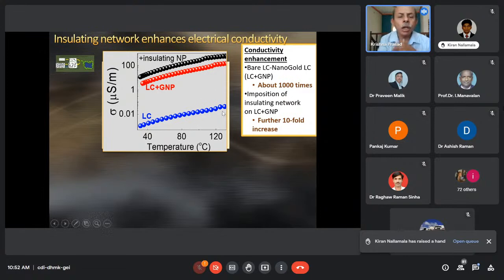What I have shown here are the temperature-dependent conductivity measurements in three different systems. One is a liquid crystal, which is behaving like a true insulator. Please note that the conductivity is given in terms of microsiemens per meter. And so therefore, you see a very small value of the conductivity, which again decreases as you lower the temperature. It should happen because of the Arrhenius forces which are behind the conductivity in these systems. But you add gold nanoparticles to such a system, there is a significant increase, which we already saw is because of the percolation behavior. But the temperature dependency is again parallel to that.